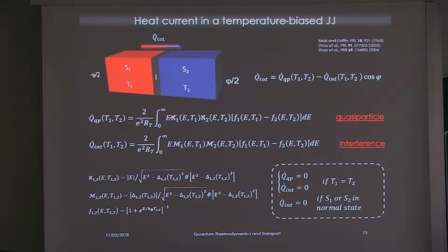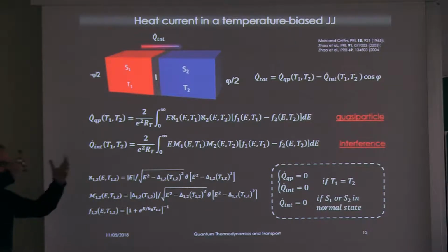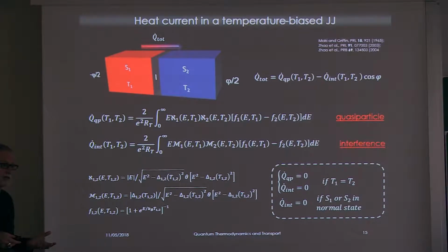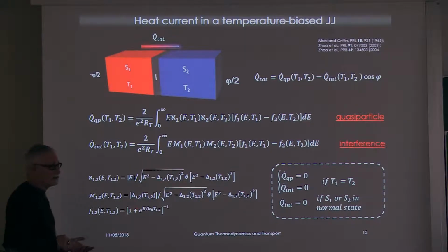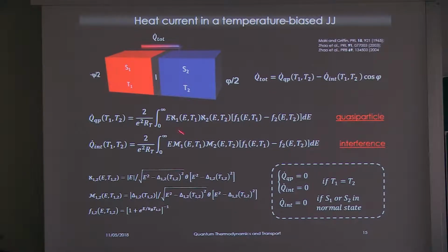The quasi-particle part is very simple. It's just the energy current flowing in the system: the convolution of the density of states of the superconductors and the difference in distribution function. So here just the density of states of the two superconductors enters. The interference part is due to energy-carrying processes, due to creation and destruction of Cooper pairs inside the system, which recombine from one side to the other in the presence of a thermal bias, and in this process they carry the phase. So this becomes a fully phase-dependent thermal process. In the language of superconductivity, this is just the component of the heat current due to bogolons. The bogolons are excitations that provide information about the phase of the system.